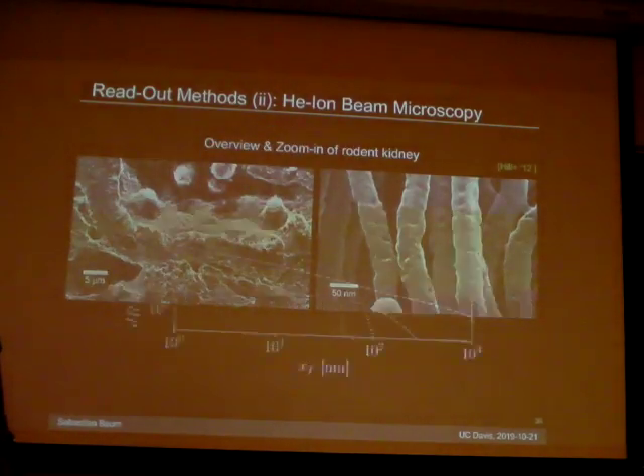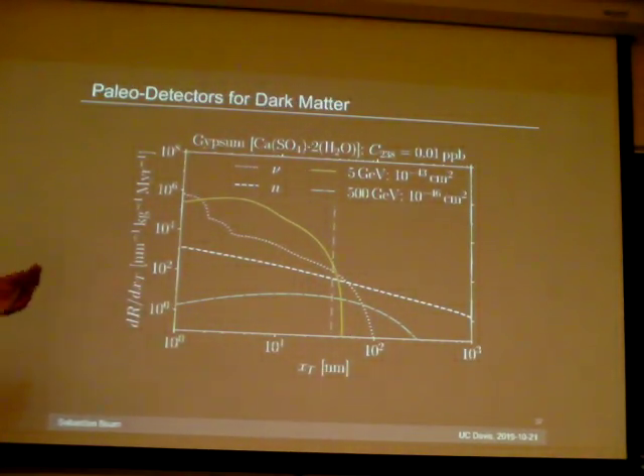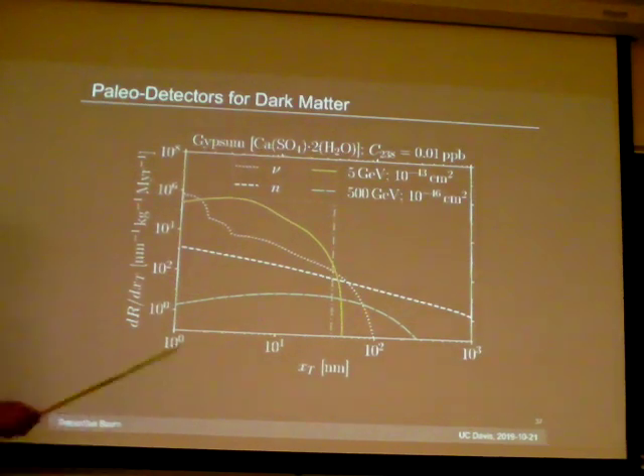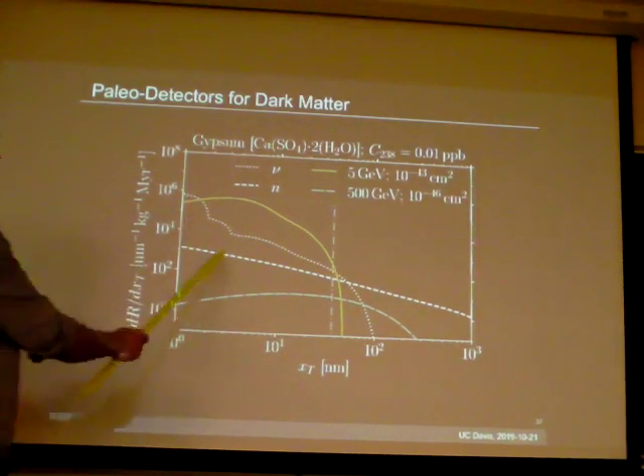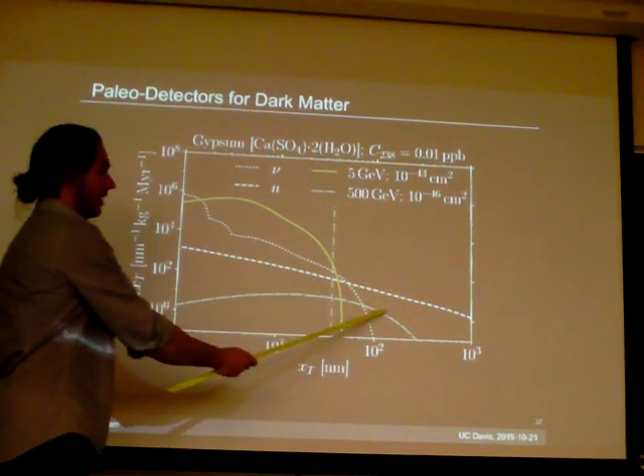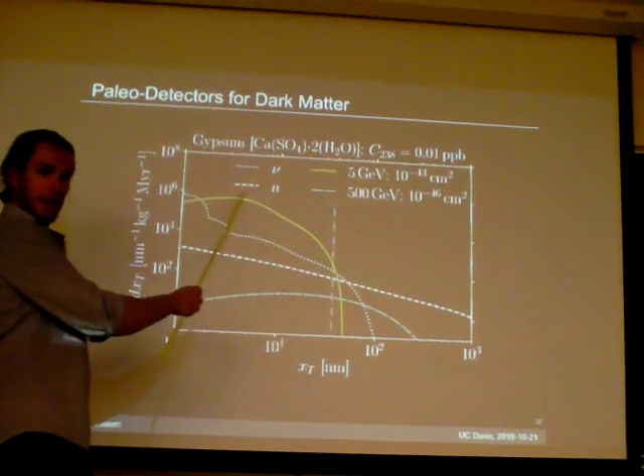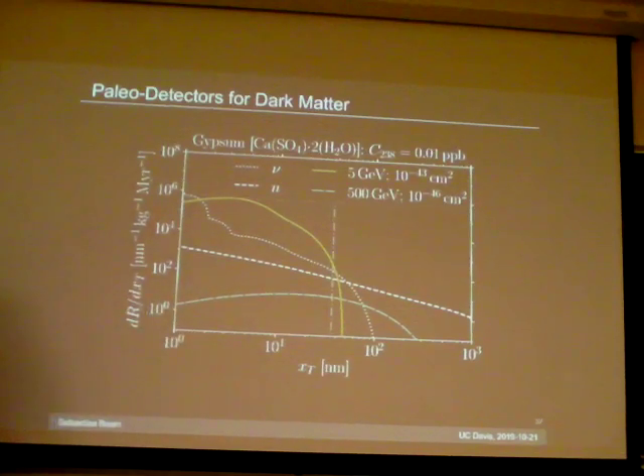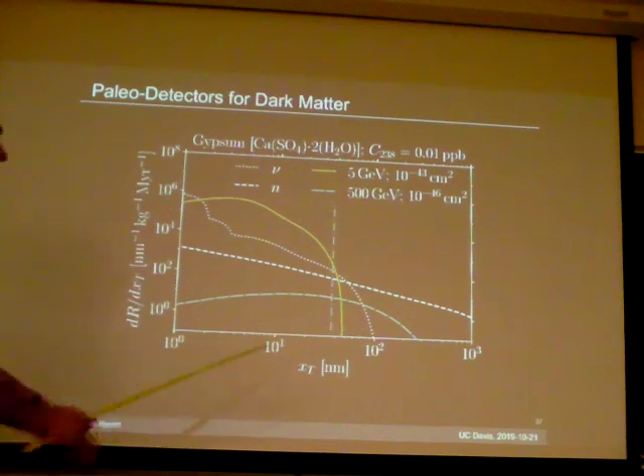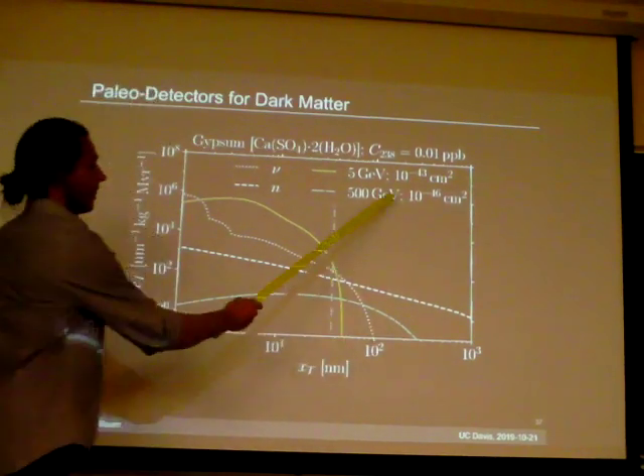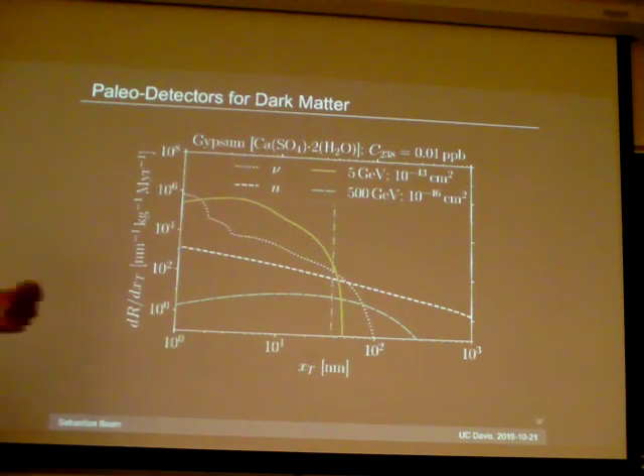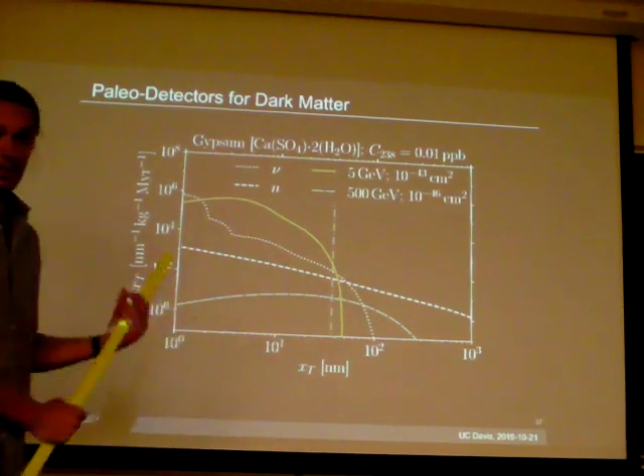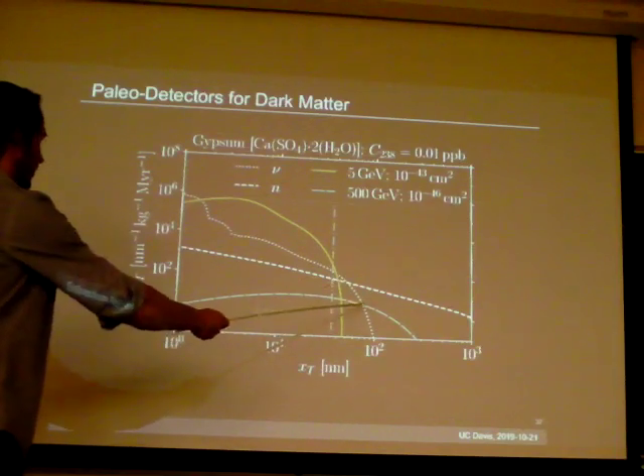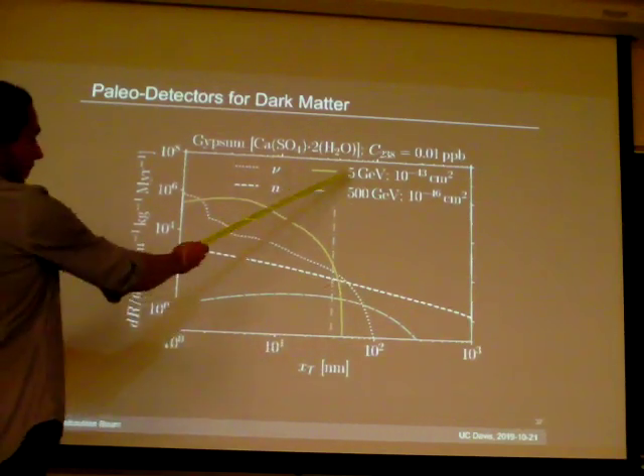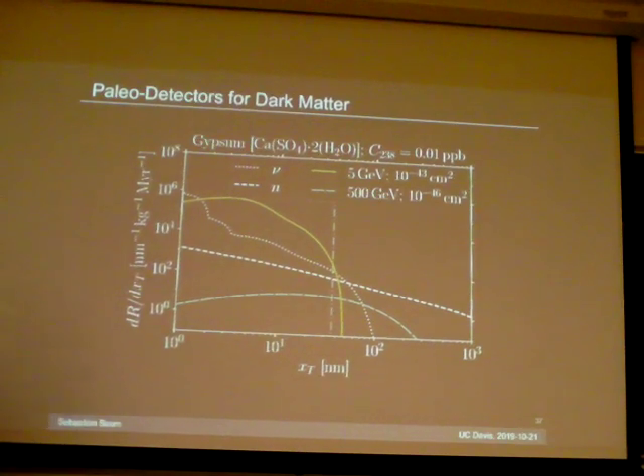So what can you do with this for dark matter? Let me show you some sensitivity projections. Just to remind you, this is the curve I showed you earlier. This was our 5 GeV guy and a 500 GeV guy. Now, if you want to look for the 5 GeV guy, you want to look here, at a few nanometers. So you want to have this helium ion beam microscopy technology I showed you about. Whereas if you look for heavier WIMPs, now you want to do the X-ray microscopy thing, because you don't need the track length resolution to be that good, but you don't get as many events here as you get for the lighter WIMPs. So you want a bigger sample.